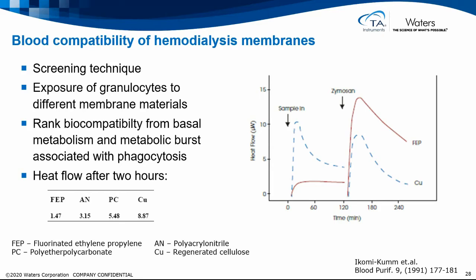Another part of the test was adding zymosan particles that would trigger phagocytosis in the granulocytes. And so it was added and the measurement continued. And for those cells that had an inert material, they had a high energetic burst due to the phagocytosis. But those materials that had already activated the granulocytes gave a much smaller energetic burst because the cells were already exhausted. So compatibility could be ranked either by the base metabolism or the actual metabolic burst that happens if you add the substance that would trigger the phagocytosis.